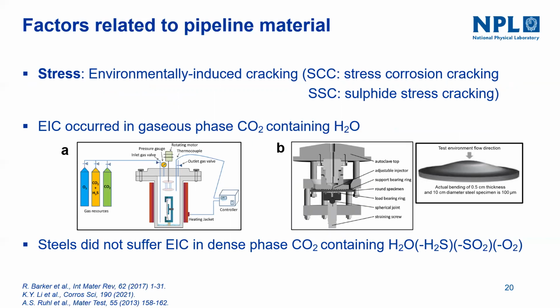And another factor is stress corrosion cracking. So EIC occurs in gaseous CO2 containing H2O. So normally, how it is tested is using the 4-point bend specimen. So everything is exposed and you see if there are any cracks on the surface, and there's a different setup here. But there are only like 5 or 6 studies studying the EIC in dense phase CO2. None of the studies reveal that these steels suffer environmentally induced cracking.